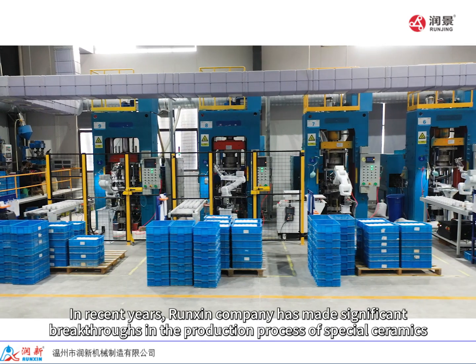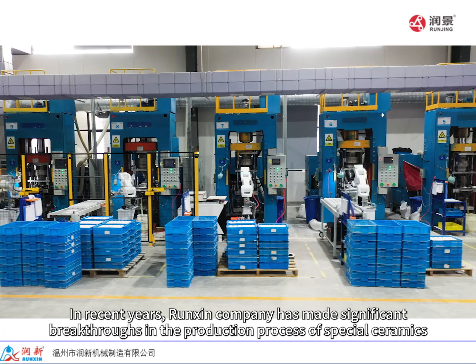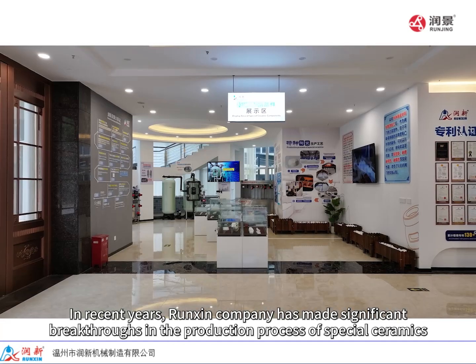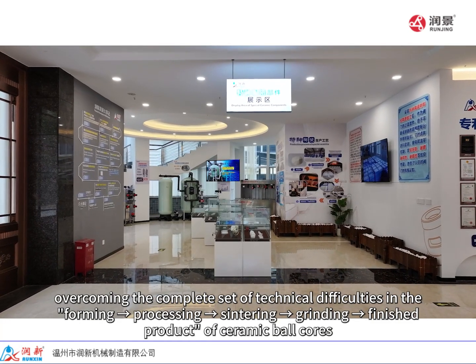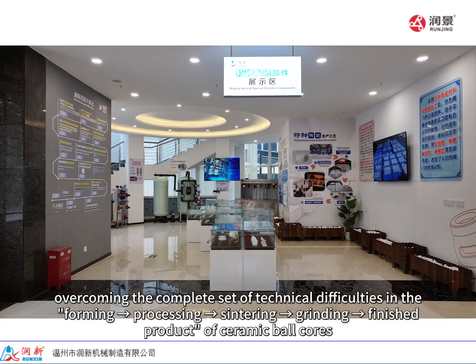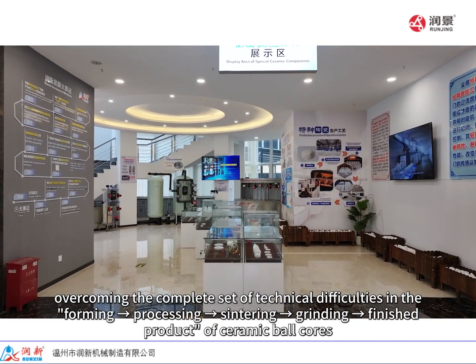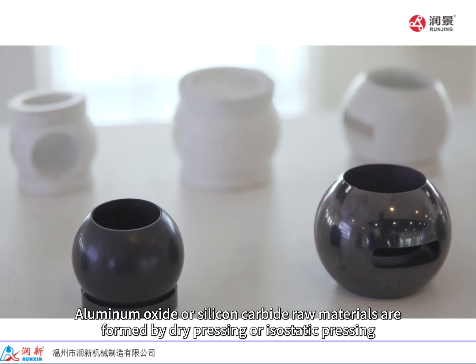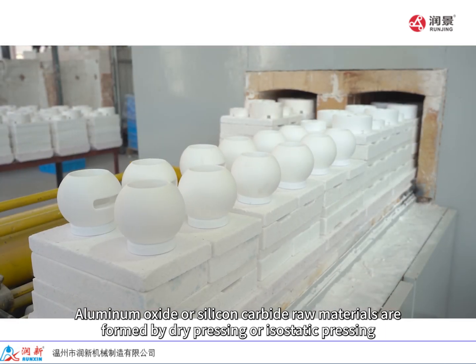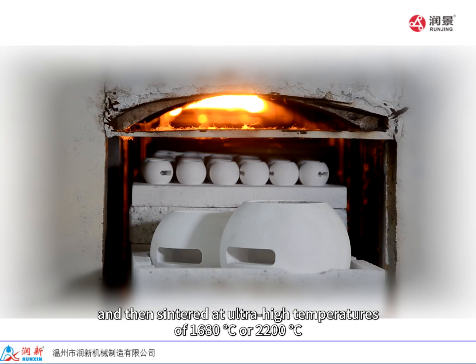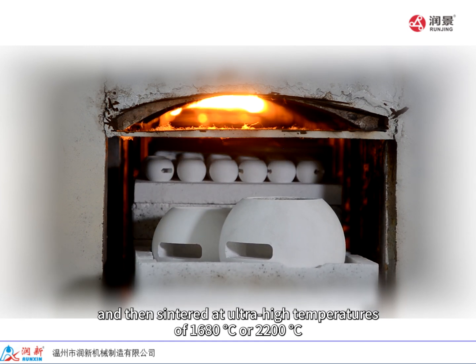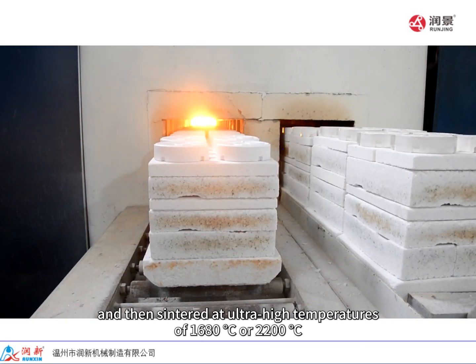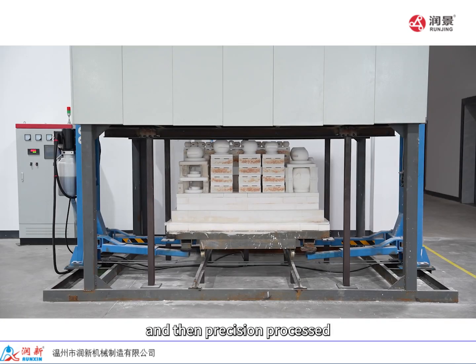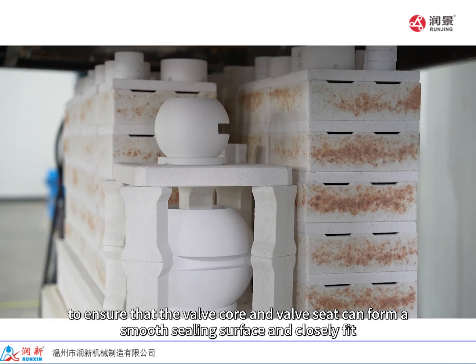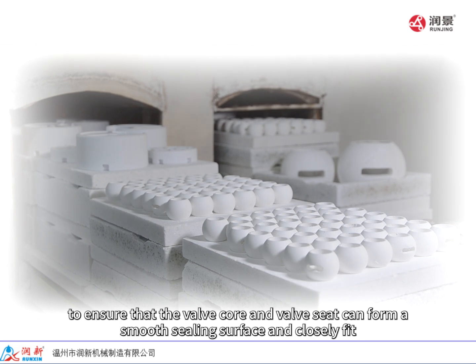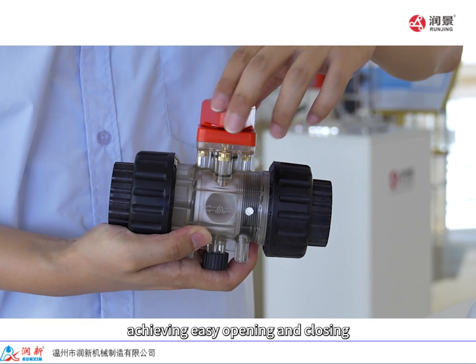In recent years, Runxin Company has made significant breakthroughs in the production process of special ceramics, overcoming the complete set of technical difficulties in the forming, processing, sintering, grinding, and finished product of ceramic ball cores. Aluminum oxide or silicon carbide raw materials are formed by dry pressing or isostatic pressing, and then sintered at ultra-high temperatures of 1680 degrees Celsius or 2200 degrees Celsius, and then precision processed to ensure that the valve core and valve seat can form a smooth sealing surface and closely fit, achieving easy opening and closing.